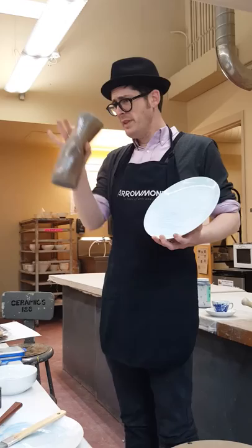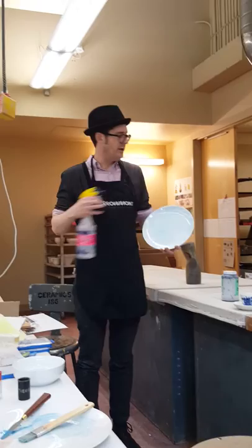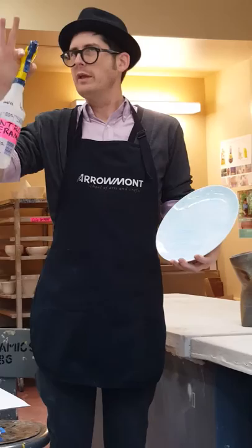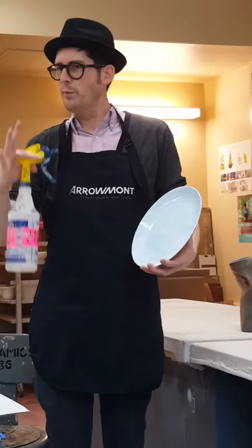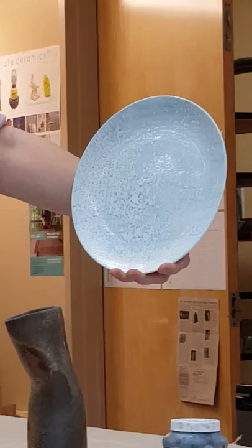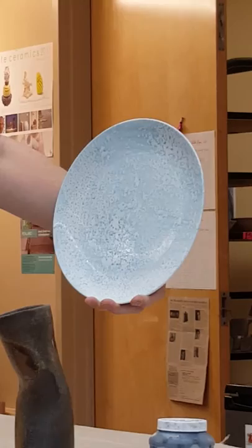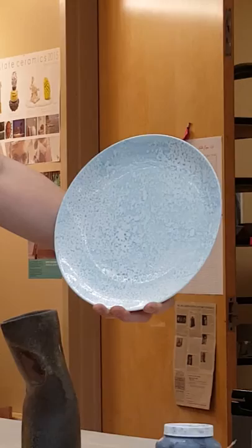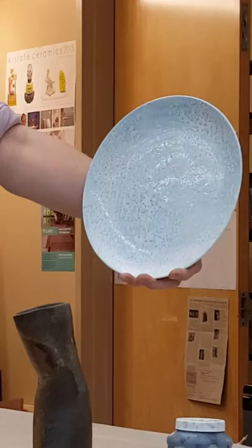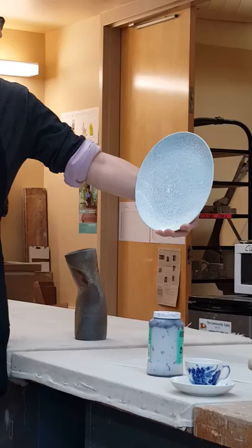There's enough silica in that wood ash that it forms a glaze like this on the outside, and if there's enough of it, it will run down. I found that baby oil and alcohol sprayed onto it — if I do it right and get my consistencies right — I can get it to sort of form a similar running consistency. There are also these amazing pink luster wares that do this with a pink shiny luster glaze sprayed with some sort of dispersant. I can fire this, put another layer on it, and build surfaces. This is my cone 016 fake soda glaze, where I have sort of an orange-peel-y texture. They hate each other, so they're fighting right now on the surface.